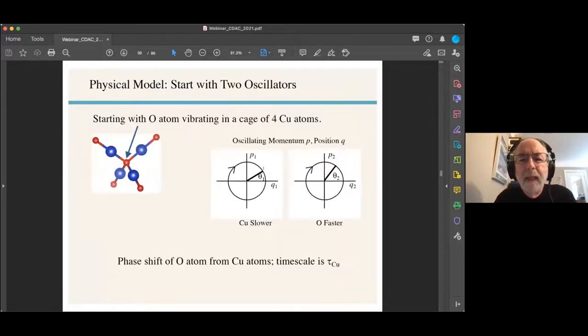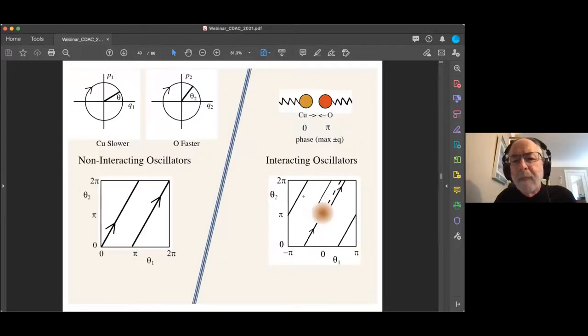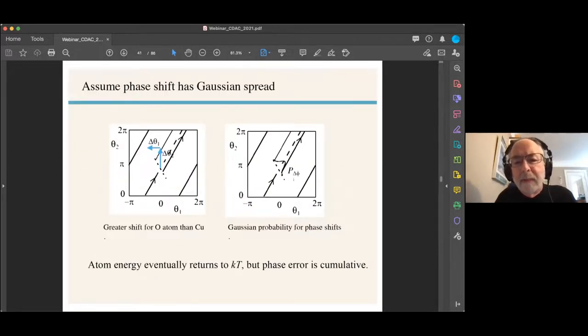So we have an approach to this, which is basically looking at how two independent oscillators, the copper oscillator and the oxygen oscillator, move independently, except the oxygen gets bumped in its phase of oscillation between momentum and position when it interacts with the copper. That only happens when the copper is in a certain position, maybe close to the oxygen, or at some part of its vibrational period, to knock the oxygen out of its pattern. It returns to kT, but the phase error is cumulative and it increases with every interaction on the time scale of a copper vibration. So we set it up as a Gaussian probability for a momentum transfer, and it happens